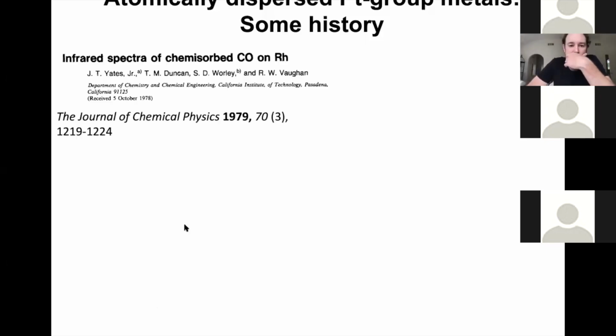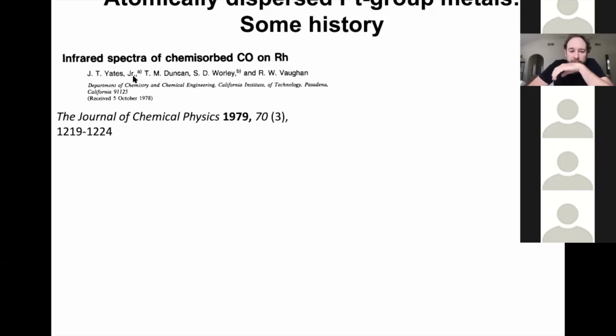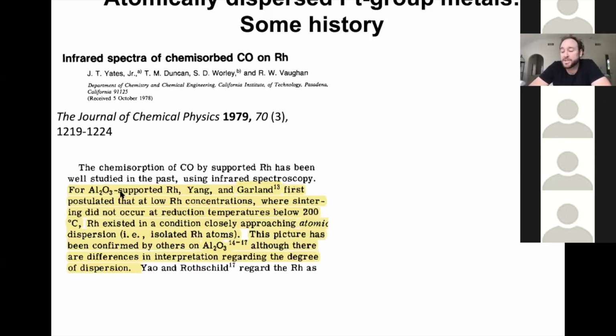So there's this beautiful paper from John Yates's group from 1979 or so, looking at the infrared spectra of chemisorbed CO on rhodium. And in it, there's a passage. And the passage here I highlight said, for alumina-supported rhodium, Yang and Garland first postulated that at low rhodium concentrations, where sintering did not occur at reduction temperatures below 200 C, rhodium existed in a condition closely approaching atomic dispersion, i.e. isolated rhodium atoms. This picture has been confirmed by others, although there are differences in interpretation regarding the degree of dispersion.